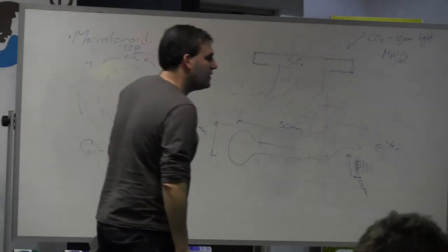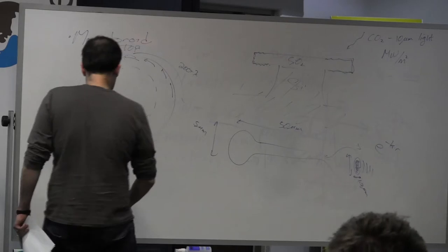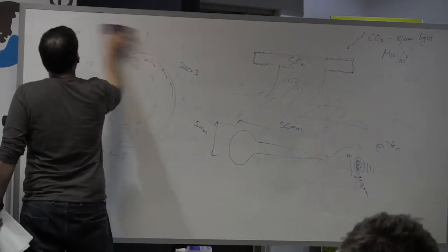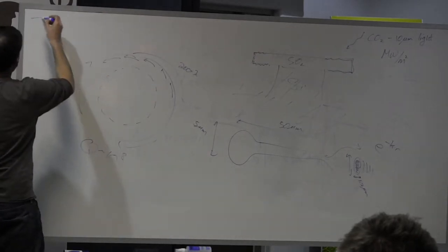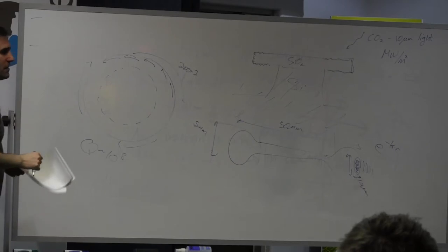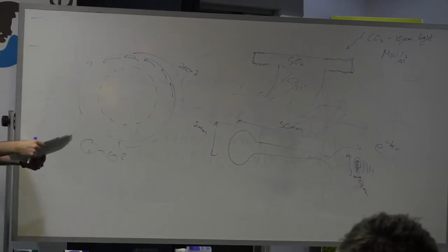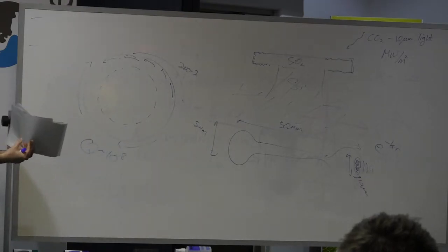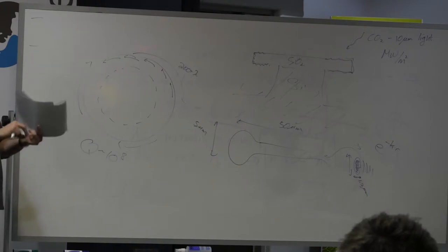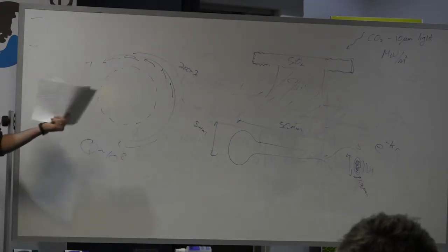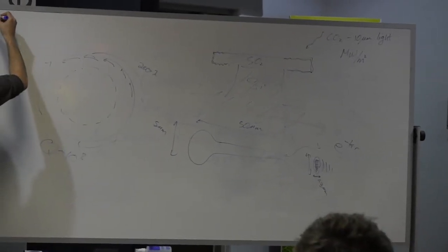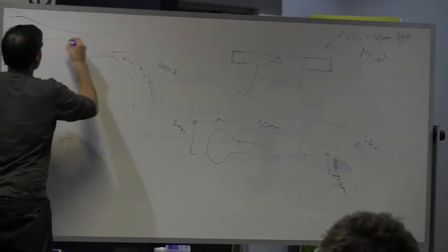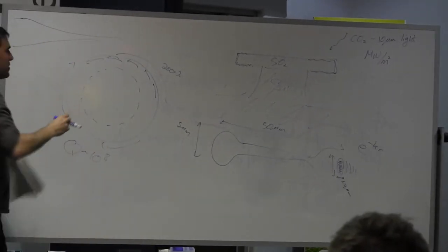How do you drive this cavity? Great. So to drive this cavity, thanks for asking, you come up with a tapered optical fiber. Here's a thick fiber, and what they do is they get regular fiber from the vendor, and they put it over a flame, and they pull. And right over the flame, the glass is pretty soft, so it stretches very, very smoothly. If you pull too far, of course, it just breaks, but if you pull just right, you end up with a very smooth taper. Again, the curvature of this thing is just guaranteed by surface tension.